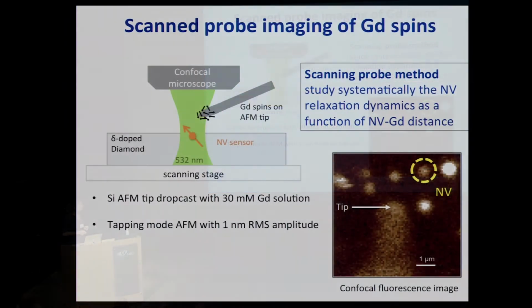So this is a combined confocal AFM microscope that we've built. Here is a confocal image showing the outline of our AFM tip, and all of these spots are single NV centers. And so we can control and position our gadolinium-soaked AFM tip to within nanometers of the NV center.